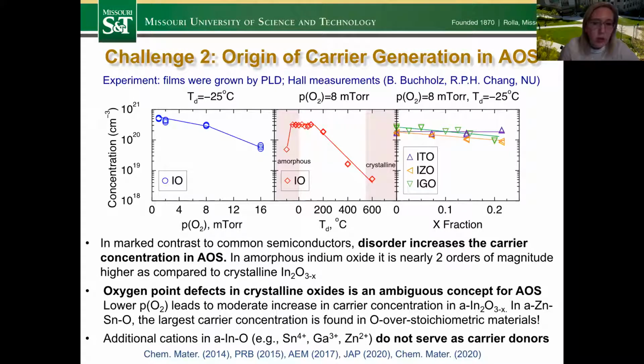concentration in indium oxide. More interestingly, even when we tune the oxygen pressure by fixing the deposition temperature at -25 degrees, so we are truly in the amorphous phase, and now tuning the oxygen pressure, the change in the carrier concentration is much more moderate. Still, of course, we can tune it a little bit, but interestingly, in other systems, for example, zinc tin oxide, the largest carrier concentration has been found for the materials that are over-stoichiometric. So we have more oxygen than is stoichiometrically expected, and still these materials have high carrier concentration, high electron concentration.